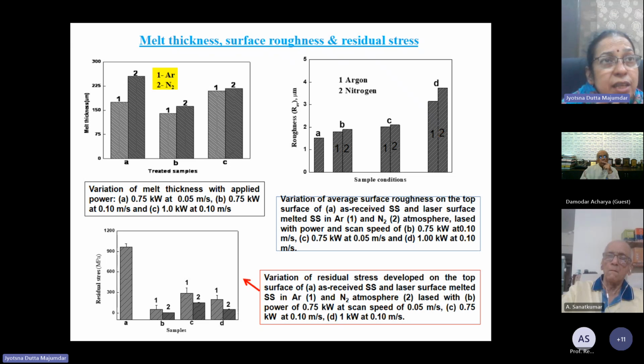And an interesting feature is that the nitride you get here is a really very high volume fraction of nitrides, which is otherwise not possible by conventional diffusion-assisted surface nitriding processing. And these nitrides are highly refined. So they are a kind of composite structure consisting of very fine nitrides distributed all throughout. Because of this structure, it offers a significant improvement in wear resistance as well as corrosion resistance, because nitrogen also is a very good element which always offers improved corrosion resistance.